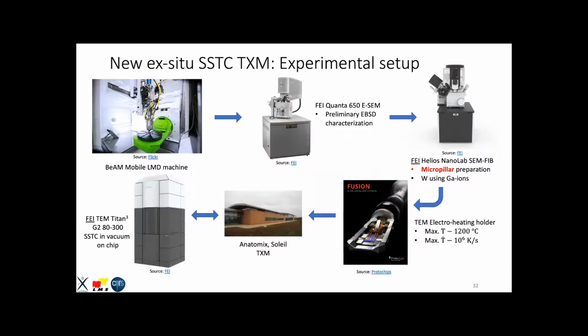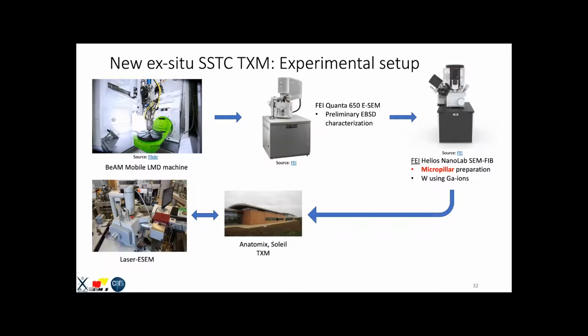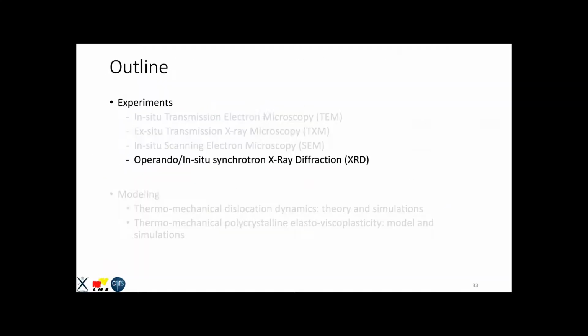Okay, so the new way to do ex situ SSTC transmission X-ray microscopy is, instead of this chip-based approach, we do the laser SEM-based approach where we prepare micropillars, go to Soleil, do the TXM, go to our laser SEM, subject it inside a controlled environment to a laser spot that is designed specifically to tackle this kind of problem, and then go back to Soleil and back and forth as much as we want.